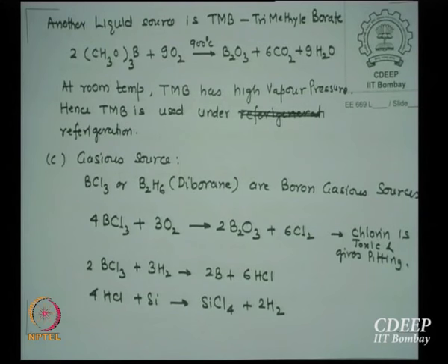BCl3 reacts with 3O2 to form B2O3 and 6Cl2, and again the same issue, it may pit, okay. Normally chlorine does not pit as much unless there is a hydrogen around. If HCl is around, it will definitely pit. But if your system is hydrogen free, it will not give that much pitting. It does react, but it has a very marginal silicon reaction. With H around, HCl, it will pit it.